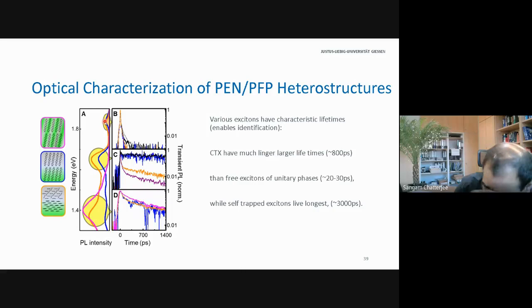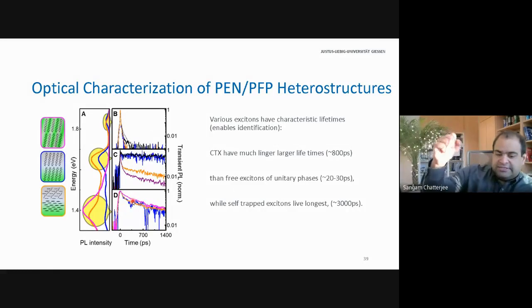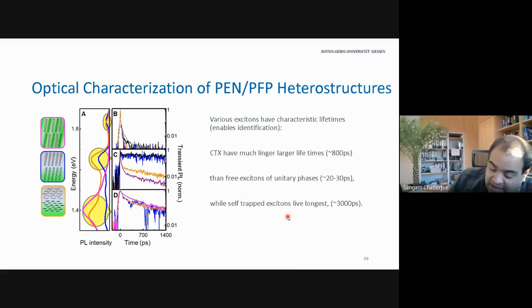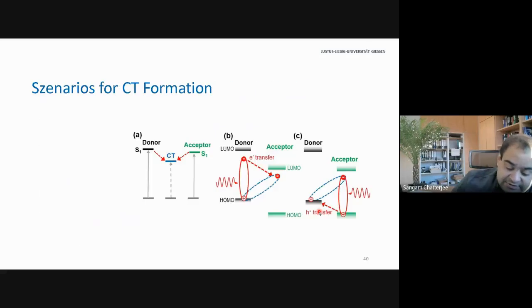So we tried to investigate this system by looking at the dynamics of all of these three characteristic resonances that we found, and they all have different lifetimes. The high energy resonances typically live very short, with a little exception, and the low energy or CT resonances live very long, and this is something you expect, because if you have an excitation which is spatially delocalized, the wave function overlap will be reduced, and this reduced wave function overlap will live longer than the unitary phases where these things can decay. We also have these little exceptions here which live longest, which are self-trapped excitons, which is basically a defect state in these systems.